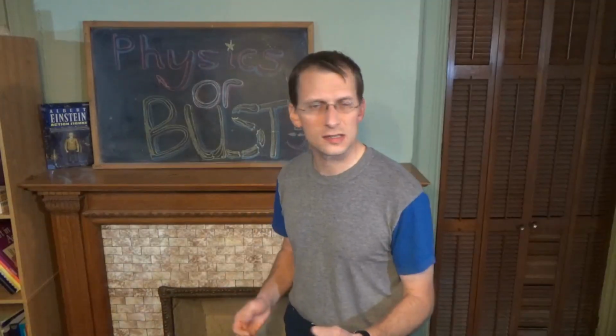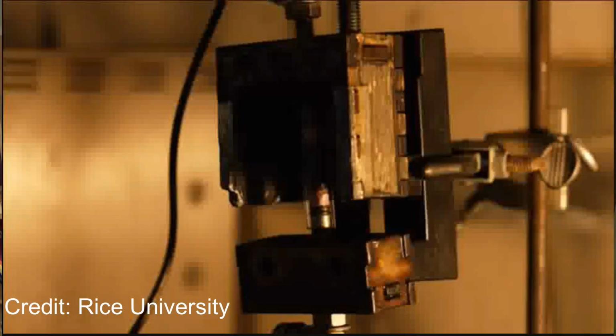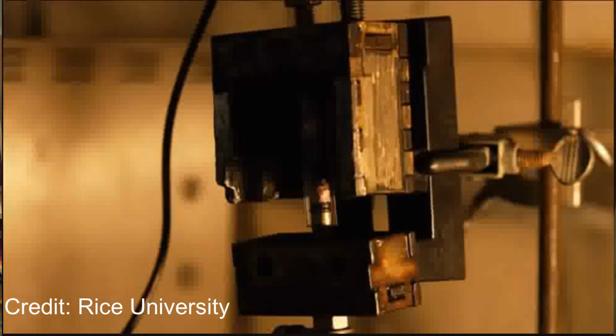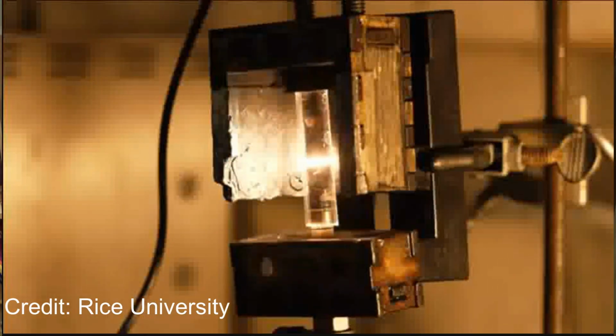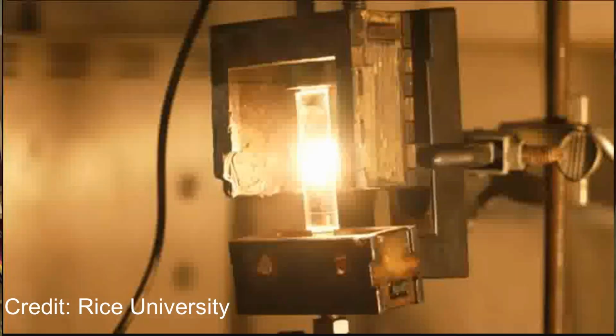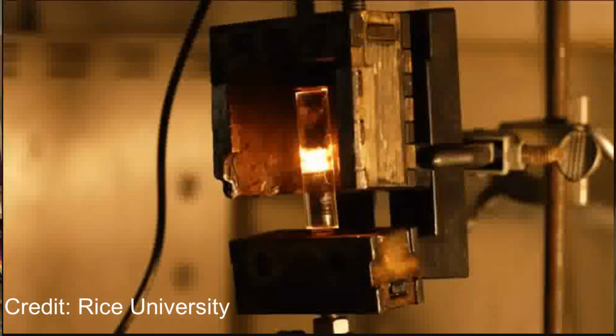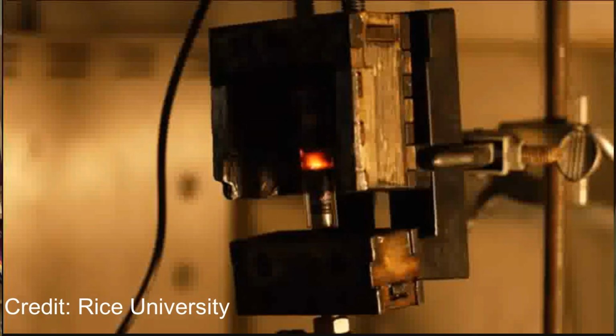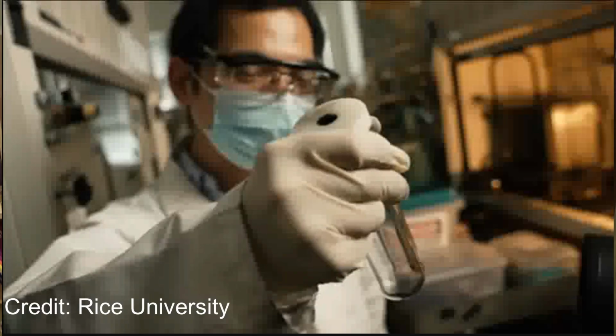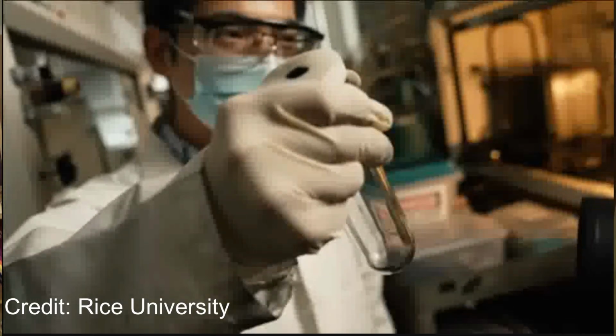So looking at the physics, there's two key features that make the flash approach work. The first is ultra-rapid heating. The sample is driven to extremely high temperatures in milliseconds to seconds. At these temperatures, kinetic barriers disappear. Reactions that would normally take forever run instantly, and volatile species can form and move before the system relaxes.